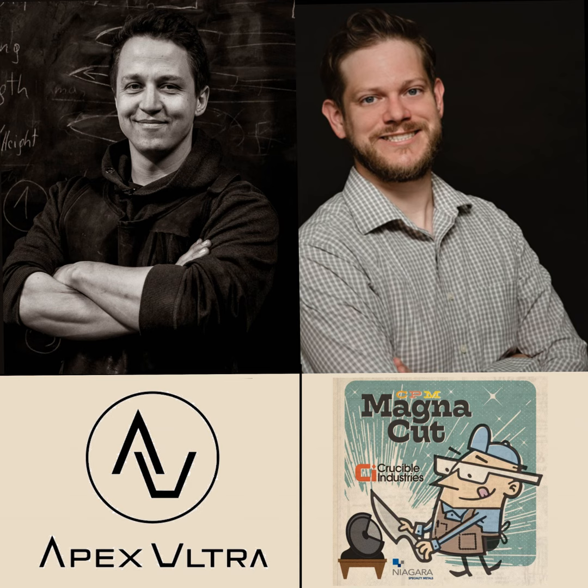Basically, you can imagine you have a block of steel that's called the electrode that is hanging from the top, and it hangs basically down into another vessel. In the bottom is the solidified part, and in the top is the starting product. And in between, you have the slag. And the slag is heated by electricity. So that's where the electroslag remelting comes from. And the slag is a very important tool in the toolbox of metallurgy to take certain elements out of the steel and to refine the steel. Whenever you want to take something out of the steel, you have to put it somewhere. And that medium is the slag. If you want to remove impurities, you have to put them somewhere, obviously.